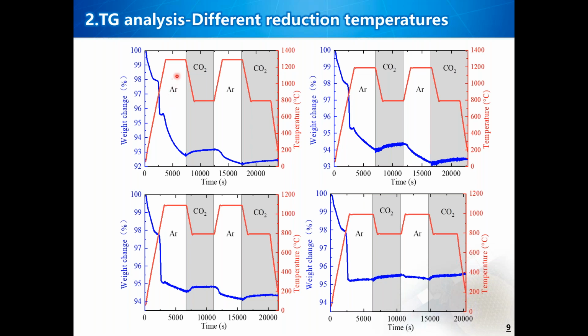The oxidation temperature maintained at 800 degrees for an hour, and the reduction temperature varies from 1000 to 1100, and so on, for an hour too. The heating rate is 20 degrees per minute. The sample mass tested was about 11 milligrams in a new platinum crucible in each experiment, as shown in the figure.